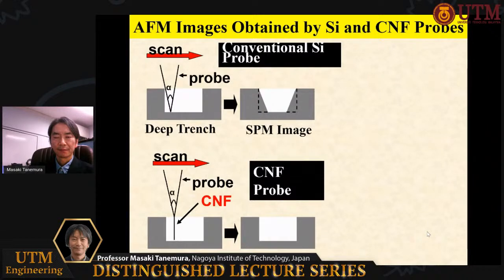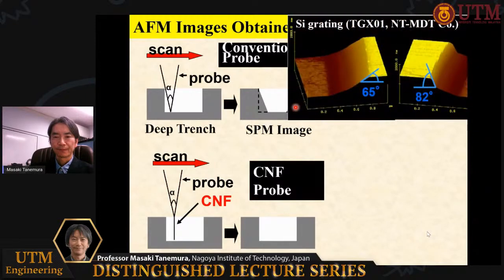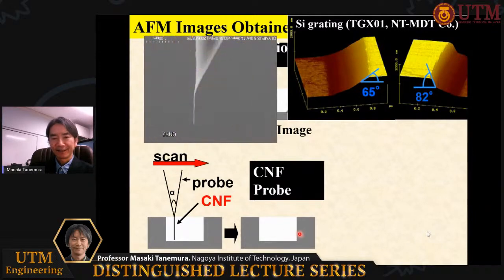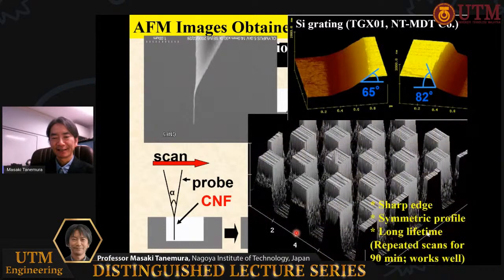What is the performance? In the semiconductor industries, the analysis of deep trenches is important. For example, this is a standard silicon grating. If we use a conventional triangular AFM probe, the obtained AFM image is not precise like this. But if we use a carbon nanofiber probe, the image should be rectangular like this. In fact, the measured profile is like this.